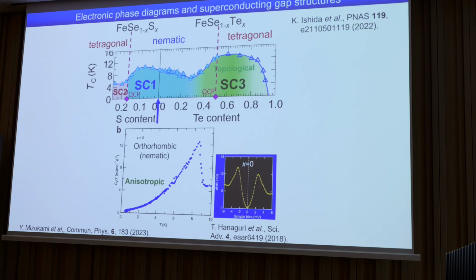This indicates that the superconducting gap is strongly anisotropic. This is consistent with the STM data showing a V shape of the dI/dV, and it's also consistent with the quasi-particle interference analysis mapping this superconducting gap anisotropy, which may have deep minima or maybe nodes in this SC1.